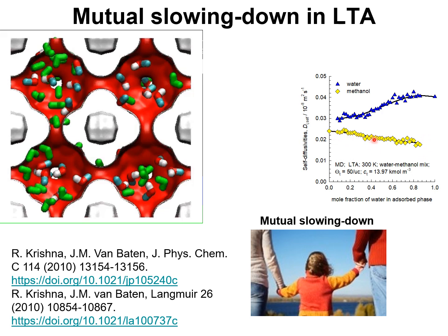With increasing water loading, the methanol self-diffusivity undergoes a reduction. Also, concomitantly, the diffusivity of water is reduced with increased concentration of methanol in the mixture. Both components undergo slowing down effects.